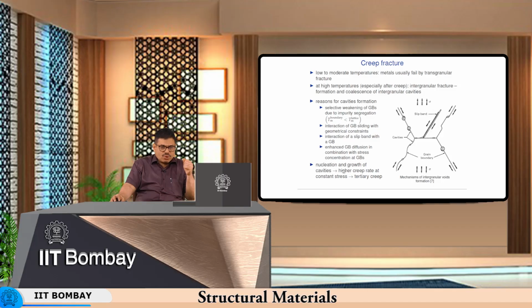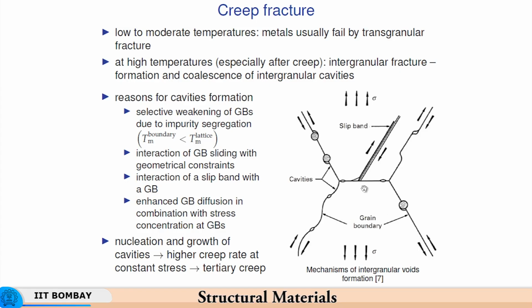And then you have nucleation and growth of cavities at high creep rates and constant stress. That is because these voids tend to grow in number as well as size, because now there is a big gap between the rate at which the voids are created and the rate at which diffusion can compensate for the material that is deficient. So, at high creep strain rates, the voids are created at a much greater rate, and the pace at which the diffusion of material takes place does not keep pace with the rate at which these discontinuities are being created at the grain boundary, and that is what leads to rapid increase in the creep rate, which is characteristic of a tertiary creep. Tertiary creep, you have a sudden increase in the creep rate at a constant stress.